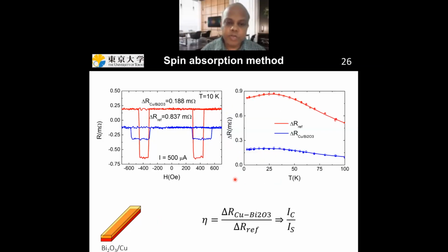We can also measure this spin absorption at all temperatures, not only at 10 Kelvin. We found that the spin current is absorbed at all temperatures. Now, if you measure the ratio between these two signals, you can calculate how much spin current is absorbed by this bilayer, and this number will be useful to calculate the spin Hall angle.